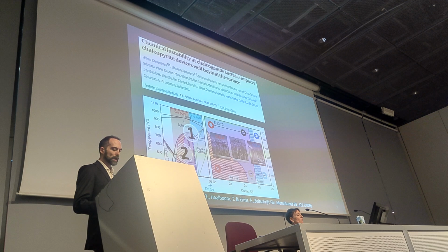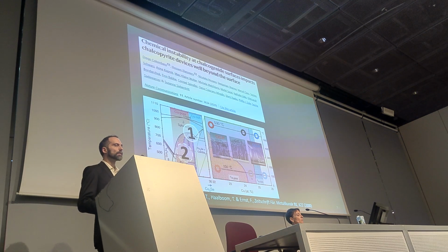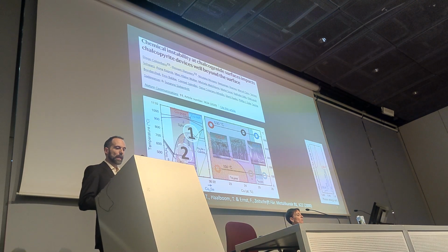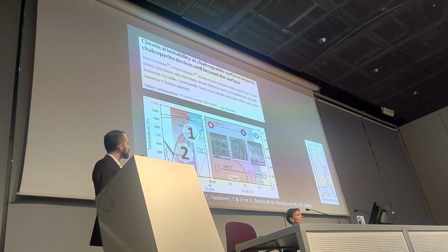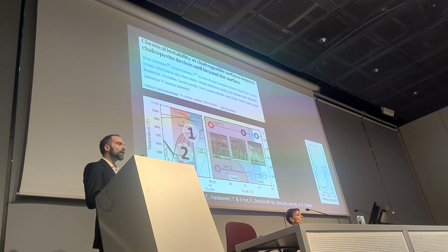Now we can also probe the electronic properties of this material by photoluminescence spectroscopy, and we see here the signature of these two extreme cases. Copper poor, you see, has a very broad luminescence emission compared to the copper rich. It has more defined patterns. So from these two pieces of evidence, we would conclude that the copper rich material should be a better material to make solar cells. It has larger grains, it has a better luminescence signature, but this is not the case.